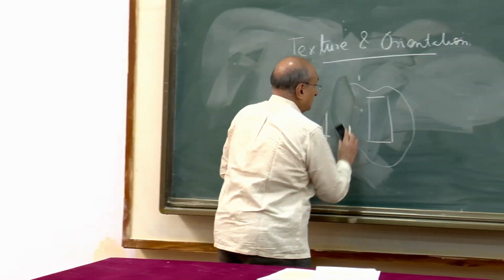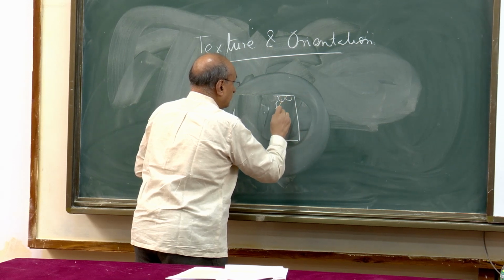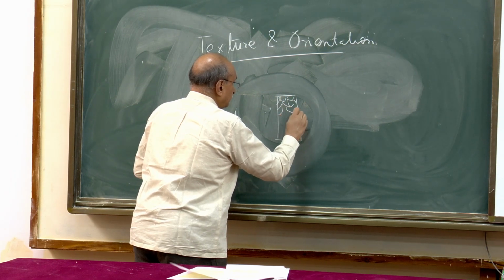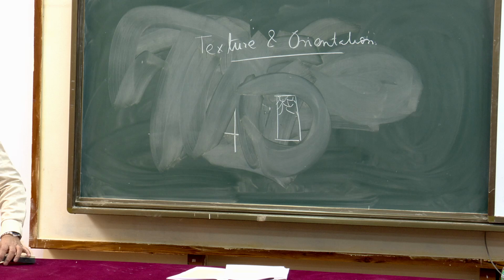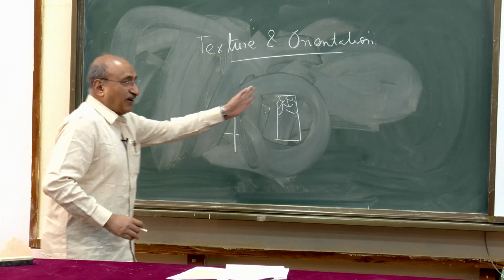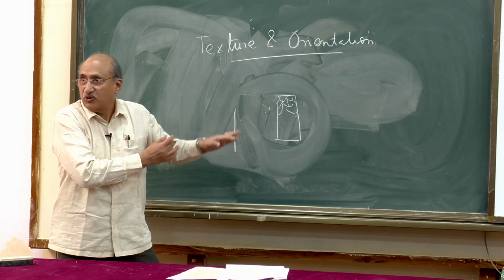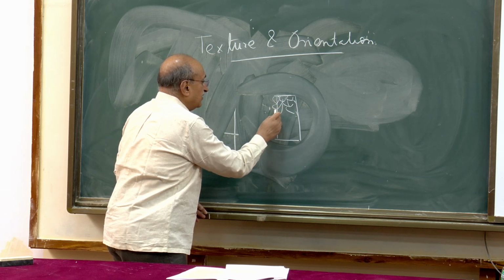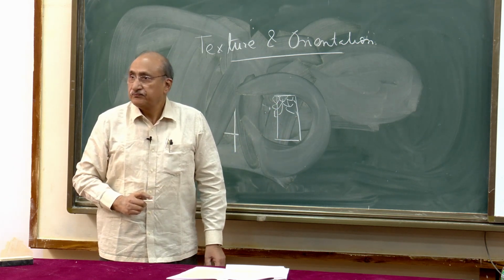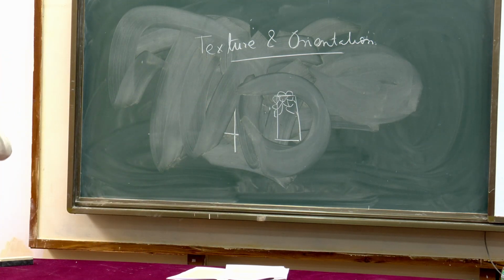Normally, a bit is written over many grains of particle size. So within this particular bit, there will be multiple grains. And if grain sizes are larger, you cannot cut these grains like this. Some will go outside this particular bit also. Some will become like this, some will become like this. Eventually you have to cut through some of the grains, which essentially creates noise.